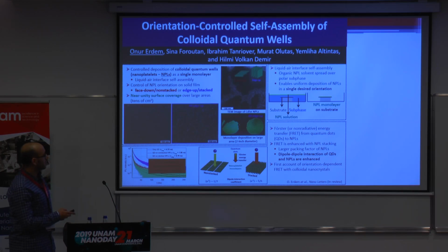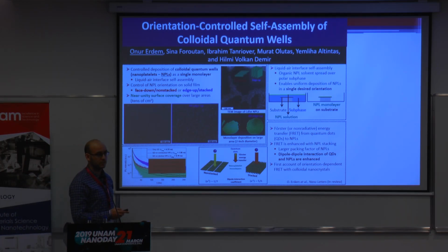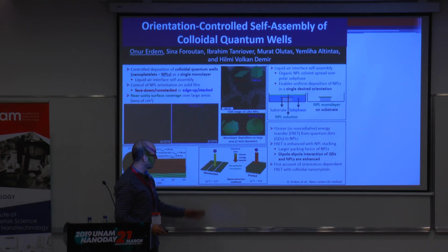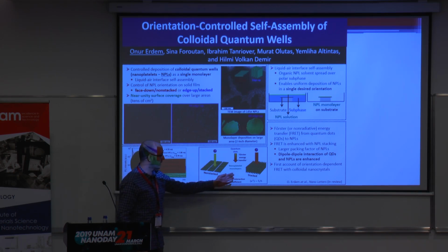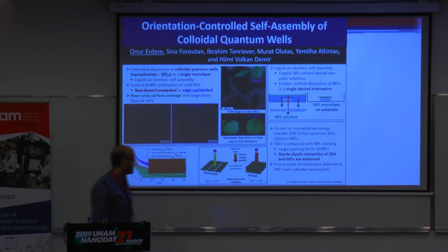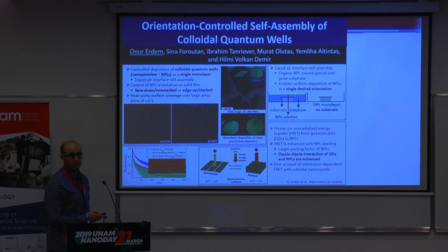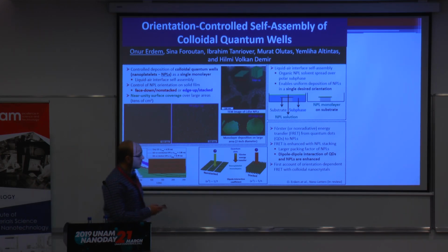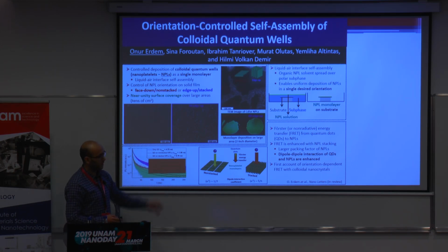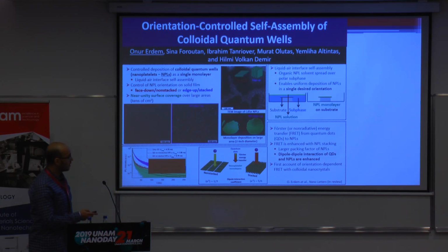So by creating these ensembles, we studied the energy transfer from quantum dots to the monolayers of non-stacked or stacked nanoplatelets. And it turns out that the energy transfer is enhanced when the nanoplatelets are in vertical orientation, mainly because there's a larger packing factor of vertical nanoplatelets, and also the dipole-dipole interaction strength is greatly enhanced when the nanoplatelets are vertical. And we also verified this experimentally.